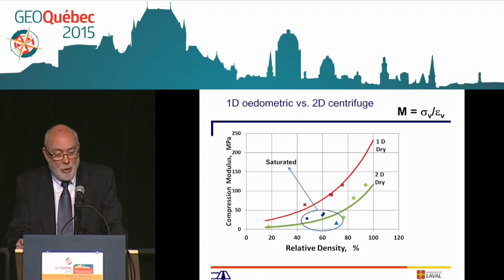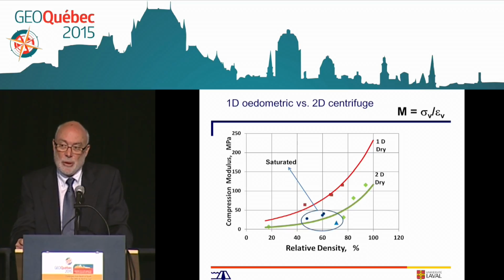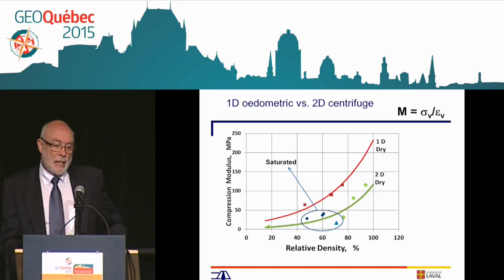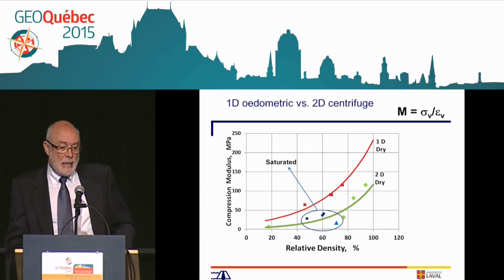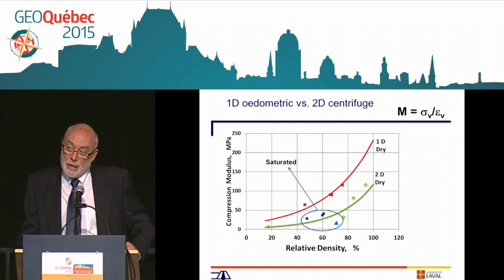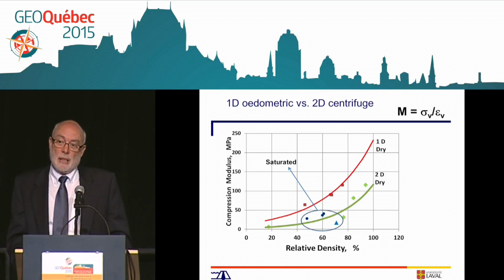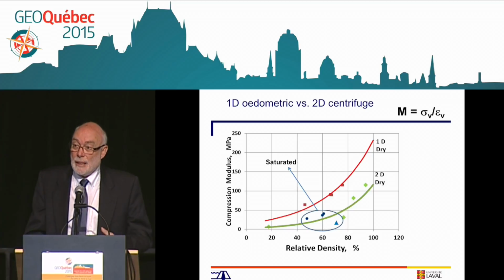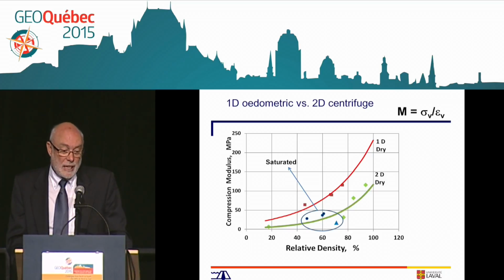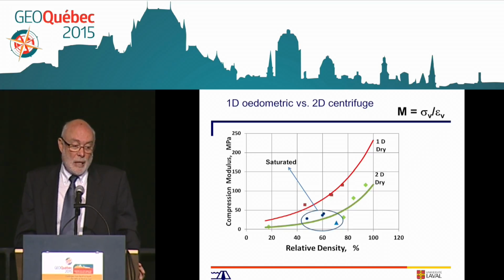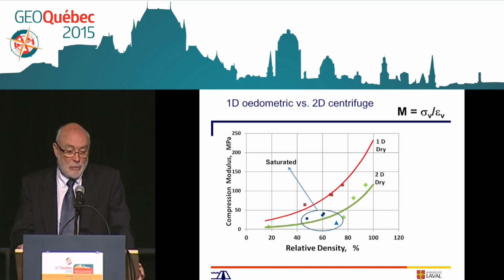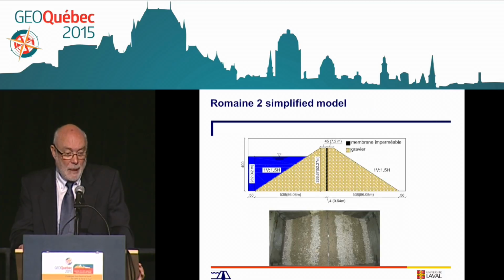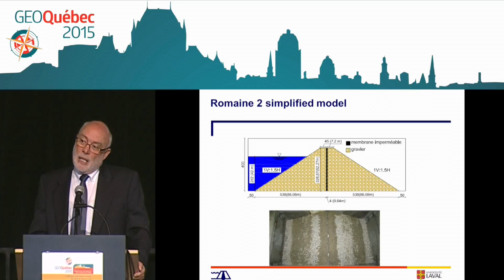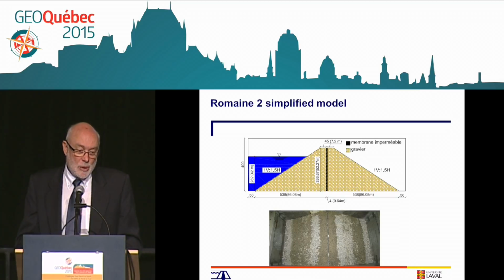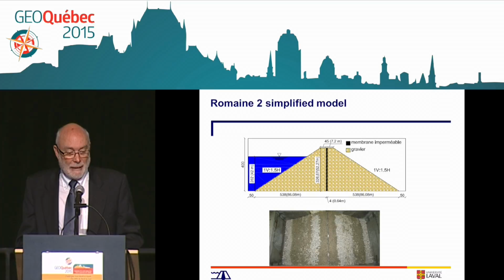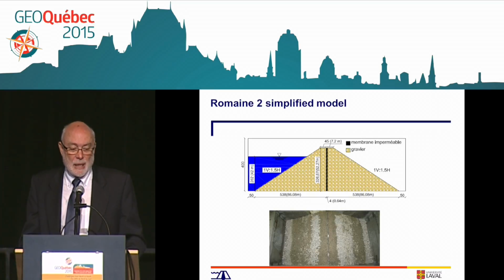We can express the same graph in terms of compression modulus, that is simply the ratio of stress divided by vertical strain. But then again, the oedometric compression test results on the same material would indicate that it's a stiffer material, hence we got less vertical strain, and the centrifuge will lead to about half of that modulus value compared to 1D. Then, knowing that the centrifuge can be used to model a simple situation, we have a simplified Romaine 2